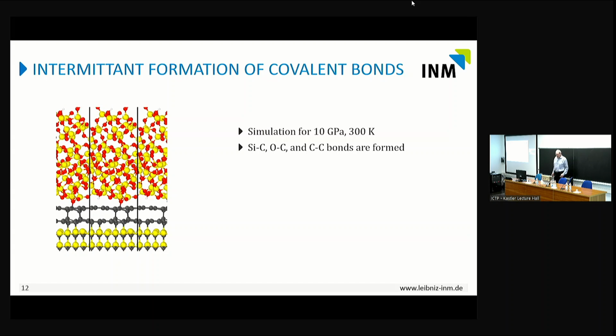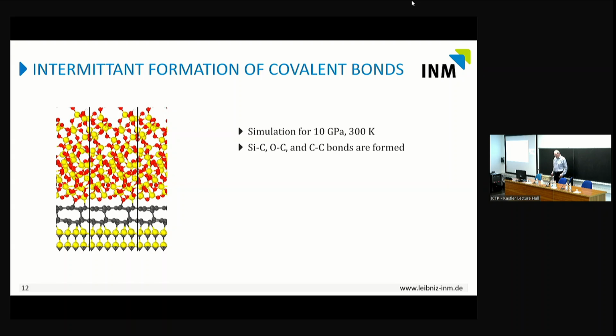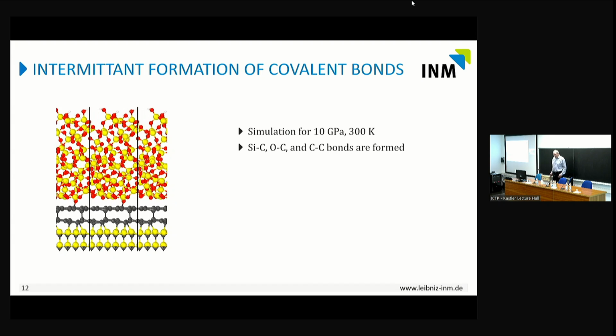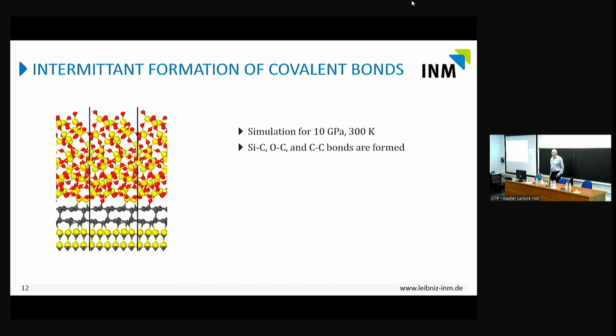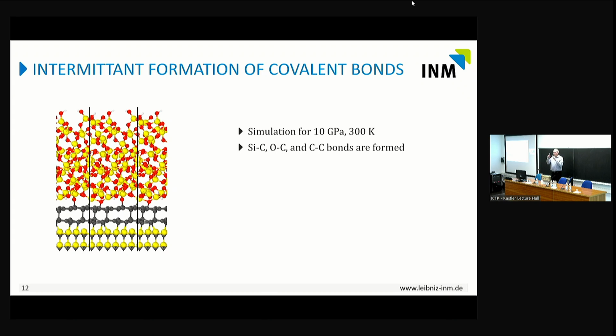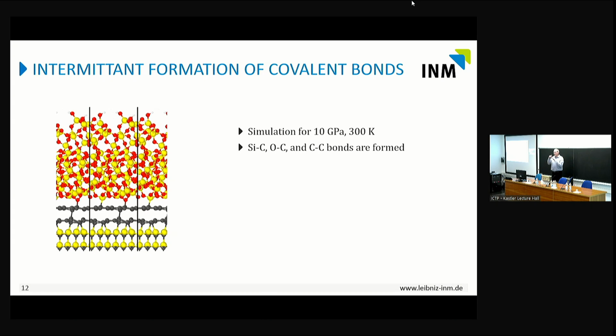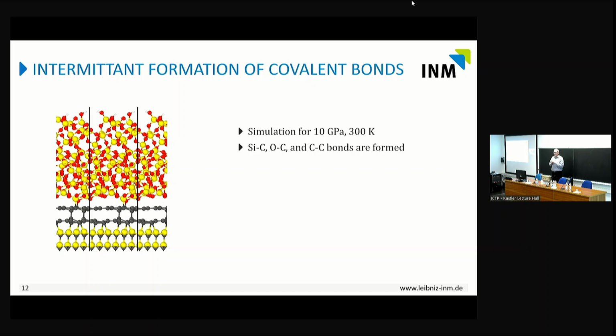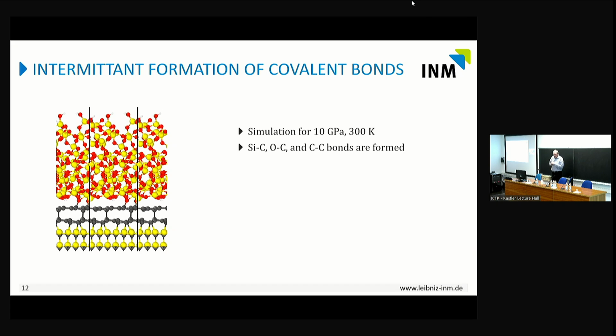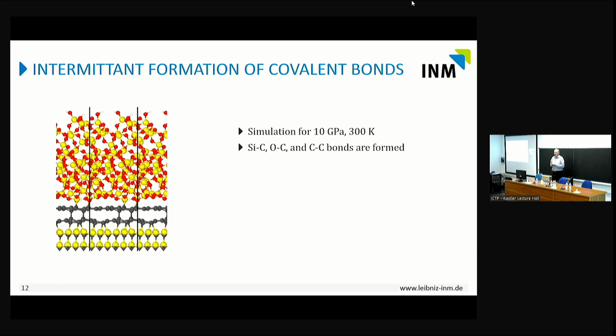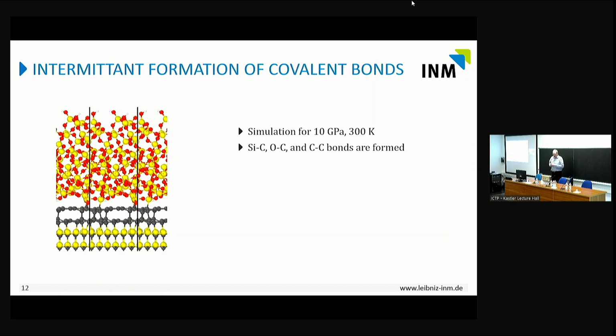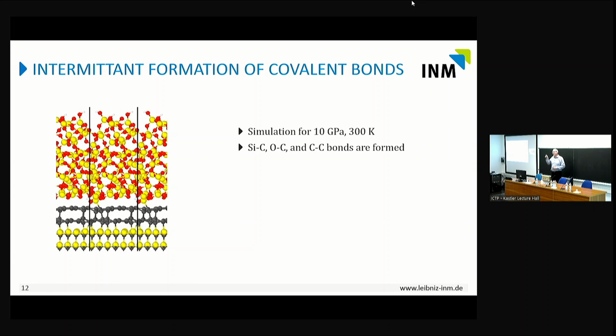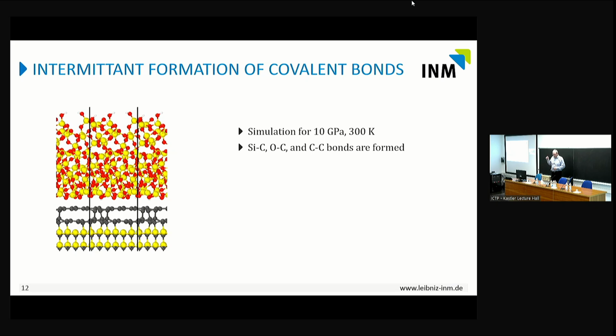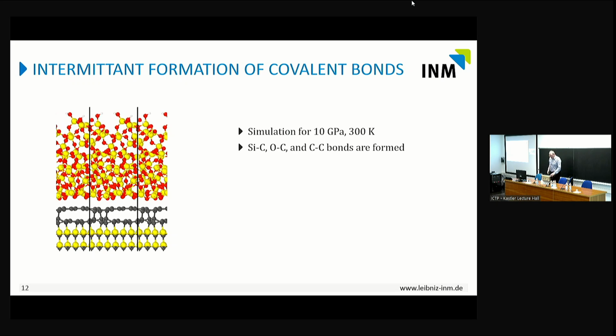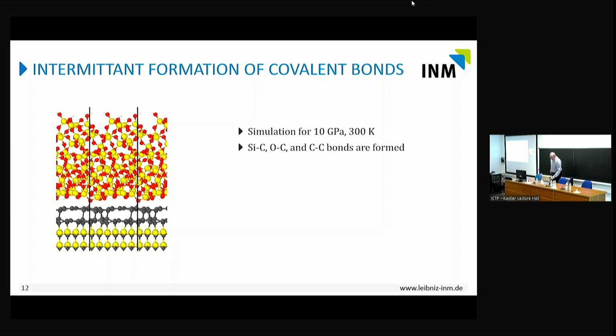So this is equilibrated, and then it starts sort of sliding at some point, I believe. And what you see is that there's actually a couple of things going on. The first, we do have bonds in the graphene layer. So there's actually sp2, sp3 transition, but we also have covalent bonds between the silicon oxide and the graphene surface, and there's both silicon carbon bonds and oxygen carbon bonds. And now we got interested to see how this all works.